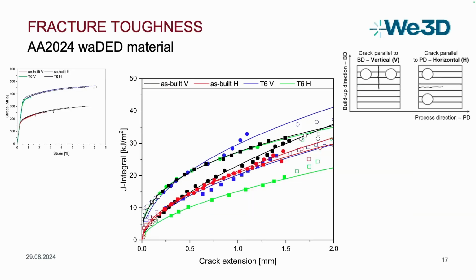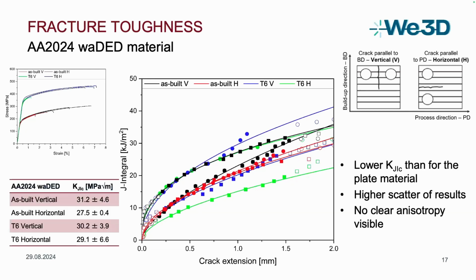The fracture toughness for the waDED material is a bit different. So we have here again all the resistance curves for as-built and T6 conditions in both vertical and horizontal orientation. But we have more of a mixture. We have a higher scatter of the specific results. We have no clear anisotropy visible. And the fracture toughness results for both the as-built and T6 conditions are quite similar. So we are at about 30 MPa root meters for both conditions.